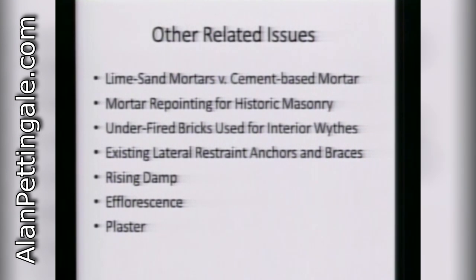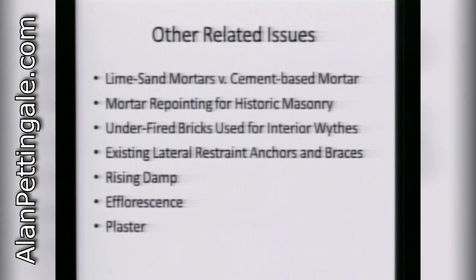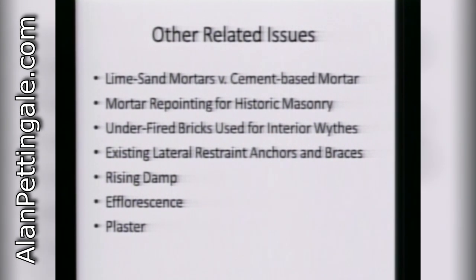However, if you have an old building and you haven't maintained the lime sand mortar, it will erode much faster because water picks up the lime and deposits it on the surface — essentially leaving you with just sand. It's very common in old buildings where literally with your finger you can swipe an inch deep and the mortar just comes away. That's a lime sand mortar where the lime has been washed out by water migration.